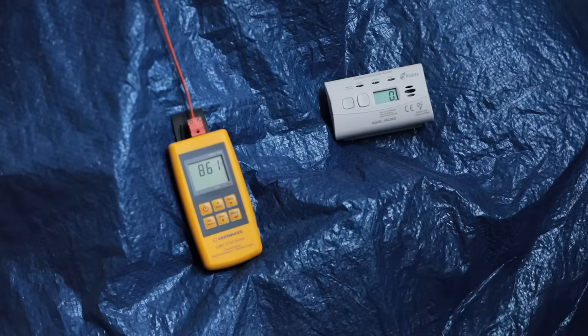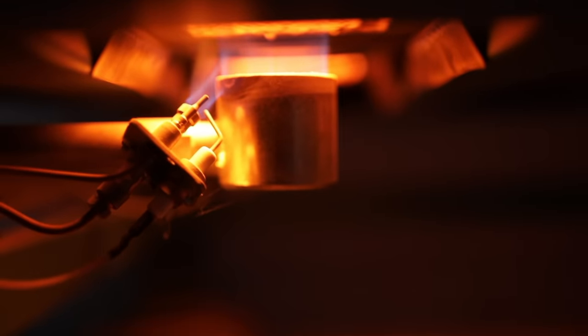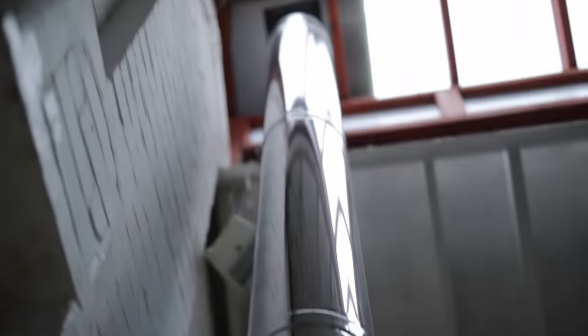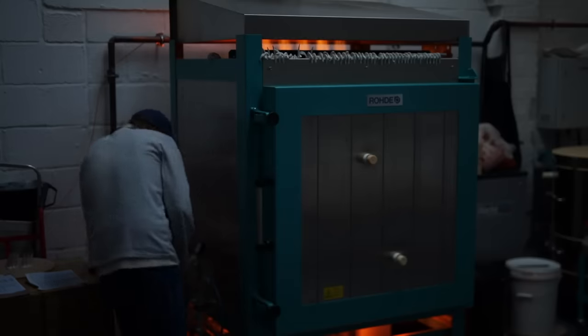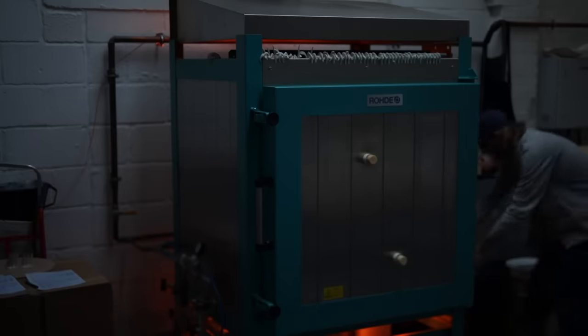A few hours later, at precisely 860 degrees Celsius, I initiate the reduction atmosphere by sliding the damper to be half closed, increasing the gas pressure and the air pressure. With the flues throttled, the excess fuel inside the chamber simply cannot burn efficiently, as there simply isn't enough oxygen. As a result, the burning atmosphere ends up stripping oxygen from inside the clay and glazes themselves, and it's this which creates the colours particular to kilns fired in a reduction atmosphere. Once the kiln reaches 1290 degrees Celsius, I can switch the gas off, and the kiln can begin to cool down, which normally takes about 36 hours or so.